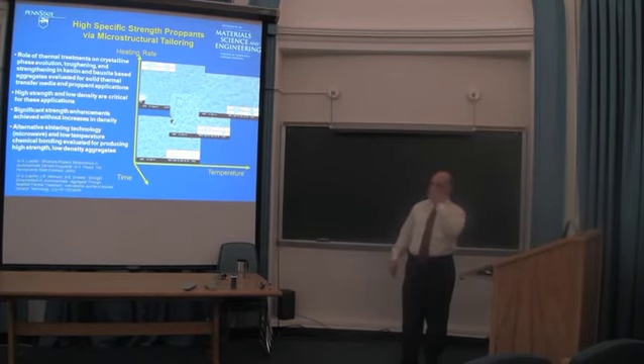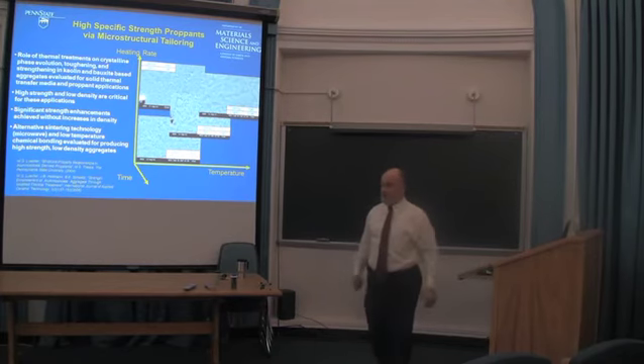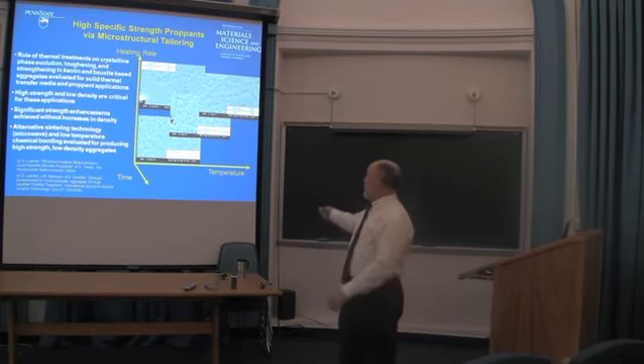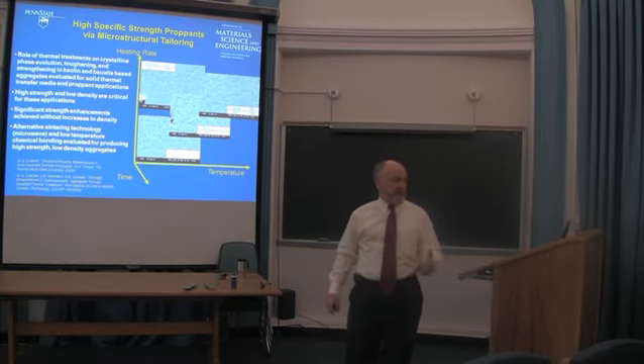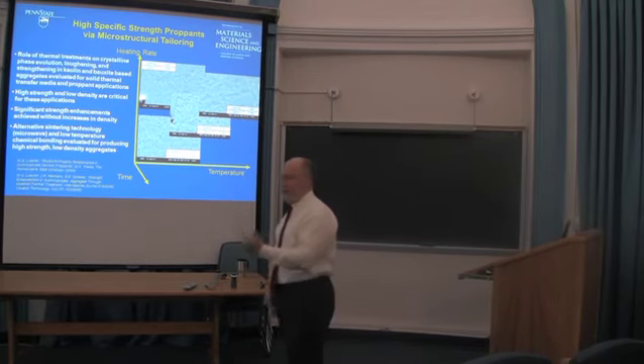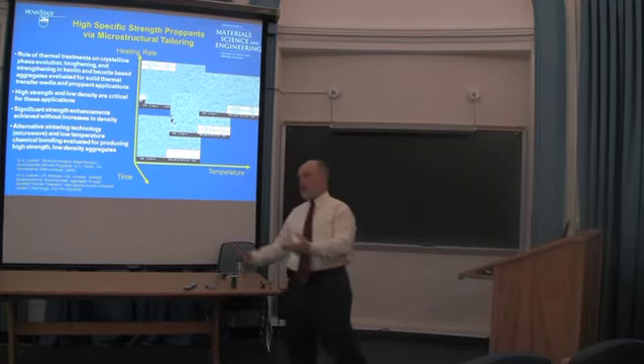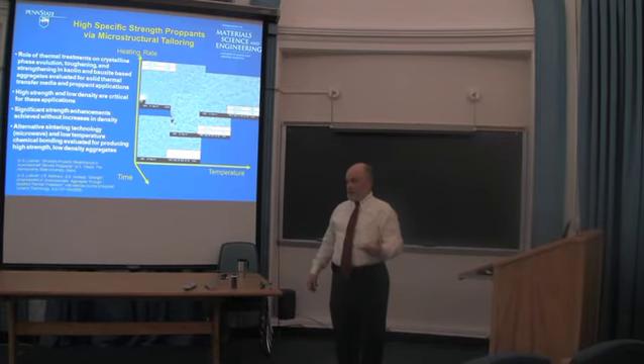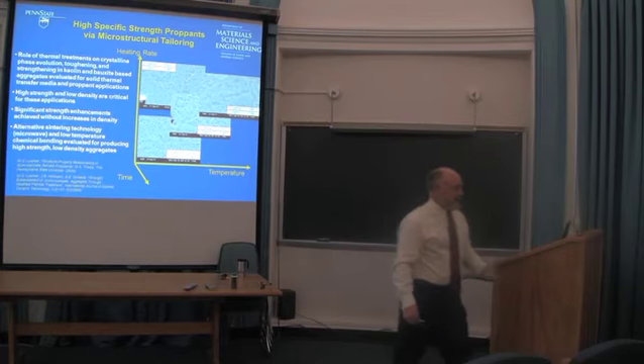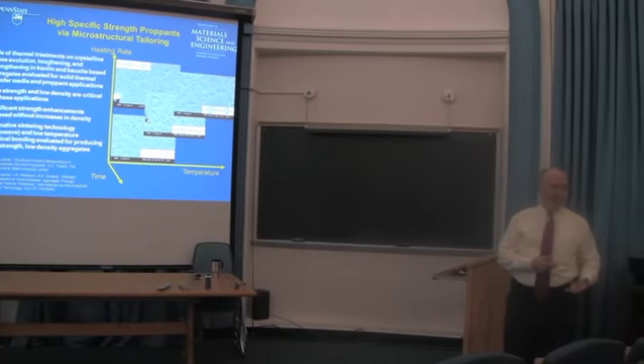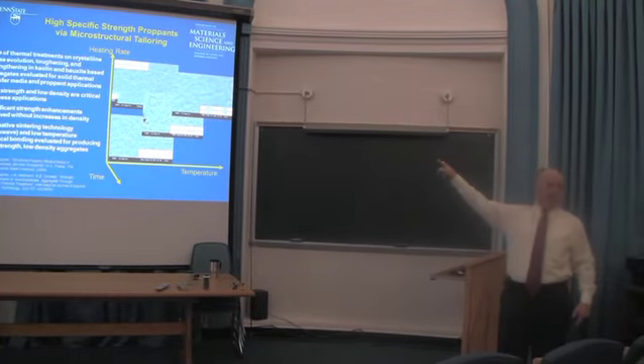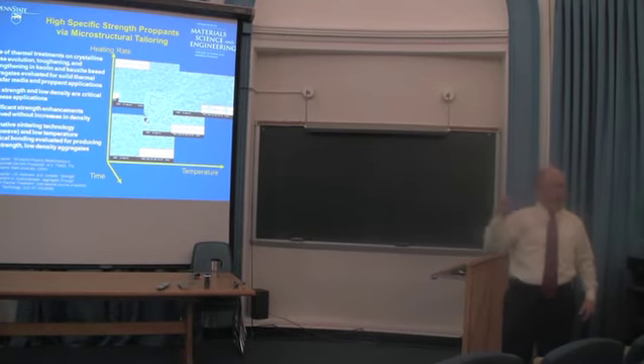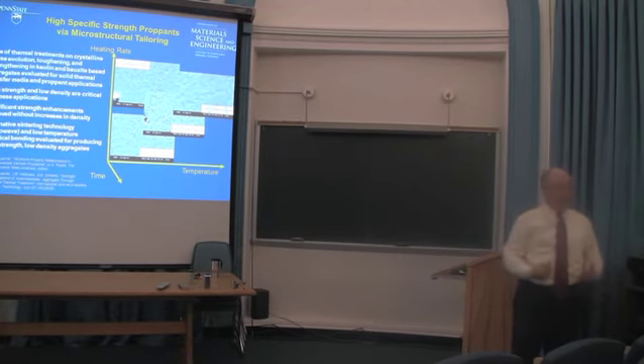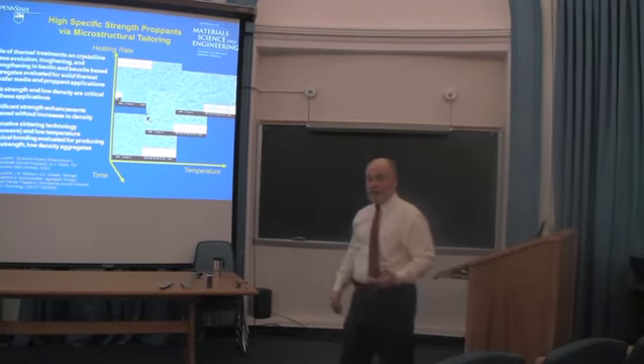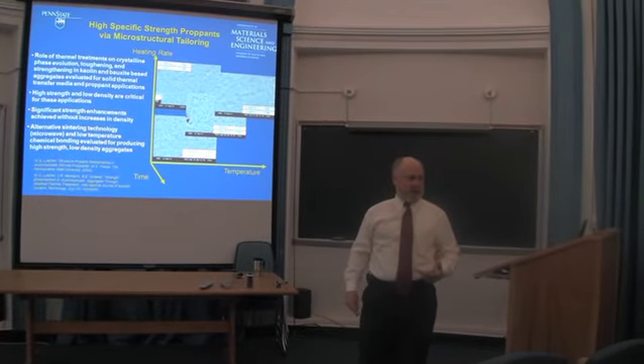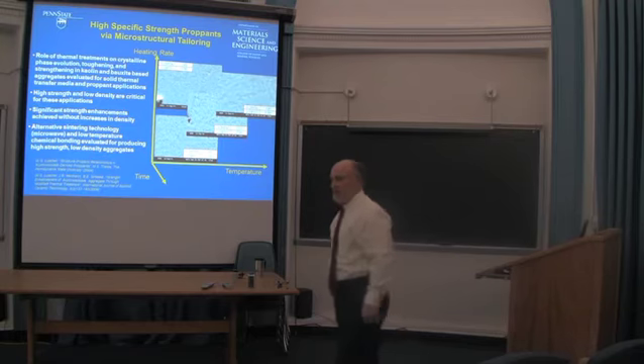what? We know something about liquid phase sintering. We're ceramists. These are liquid phase sintered. If we modify the glass phase chemistry so that we modify its viscosity and melting temperature, softening temperatures and the like, as well as the activity of different species in that glass, we can accelerate that sintering and accelerate the evolution of desirable phases and the removal of undesirable phases like cristobalite. And the way you do that is through a concept that ceramists and geochemists and so on would call doping.